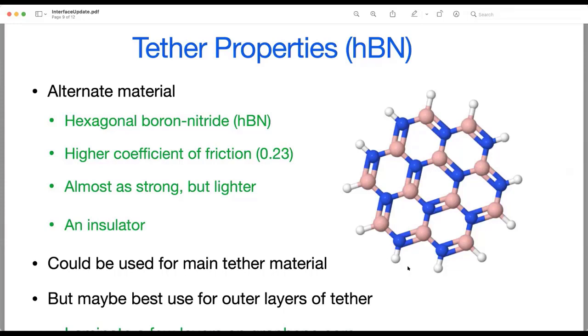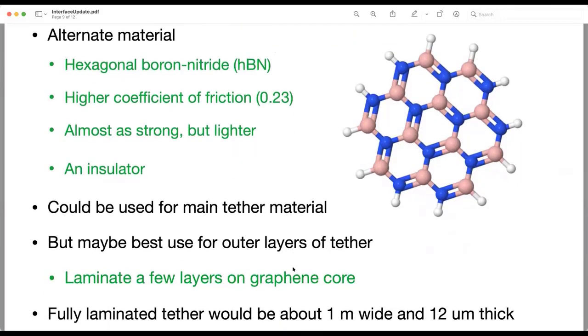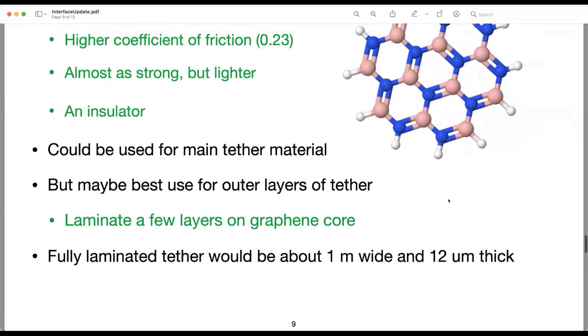And so it could be an alternate material for the tether, but maybe more importantly, it's got high friction and it's an insulator. So this may be something we need, whereas single crystal graphene is a very good conductor. It looks like boron nitride would be an insulator. So we could conceivably use hBN for the main tether material, but maybe it's best to use it for the outer layers of the tether. So we could have a tether whose bulk consists mainly of single crystal graphene with a few layers on the outside consisting of boron nitride. And such a tether would be about 1 meter wide and 12 microns thick.